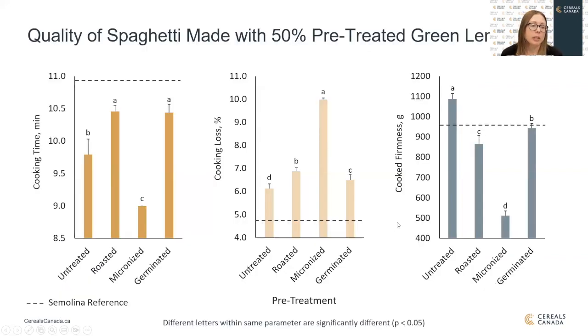So I just wanted to pull out some of our spaghetti quality data. This is specifically for the green lentil flours. And you can really see the difference that micronization had on the quality. So you see a much lower cooking time, much higher cooking loss. This is probably likely due to that starch damage.